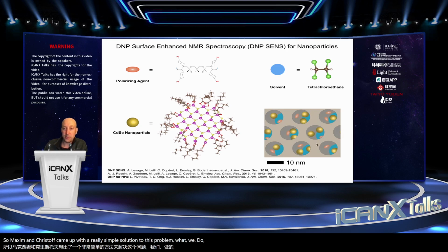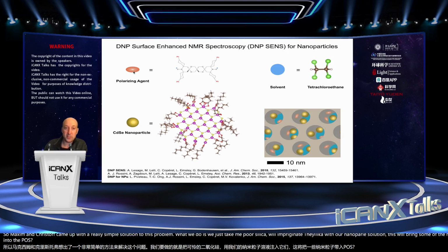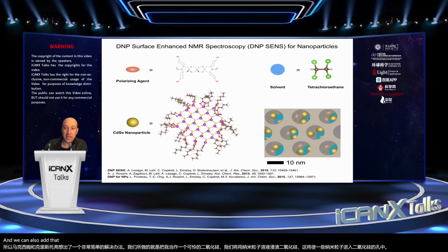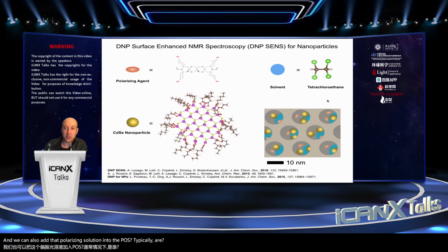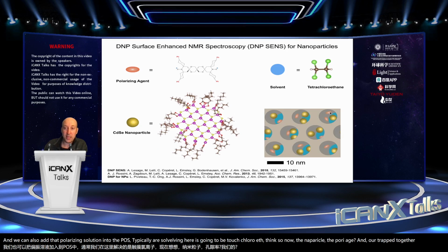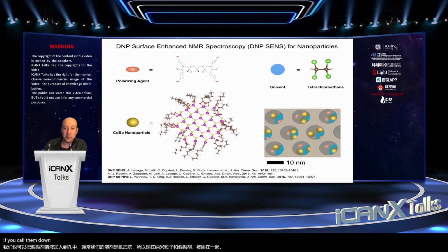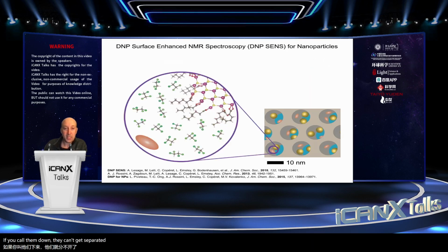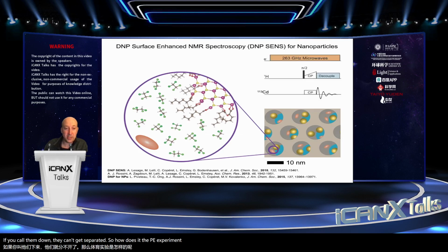What we do is we just take mesoporous silica. We'll impregnate the silica with our nanoparticle solution. This will bring some of the nanoparticles into the pores of the silica. And we can also add that polarizing agent solution into the pores. Typically, our solvent here is going to be tetrachloroethane. So now the nanoparticle and the polarizing agent are trapped together. If you cool them down, they can't get separated. So how does this DNP experiment actually work?